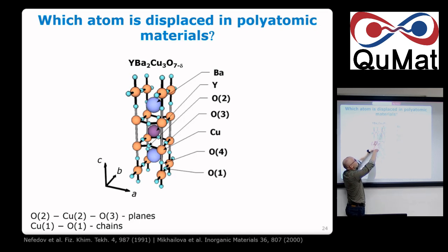Superconductivity comes from these planes. But once you change the oxygen content here, you are removing that one, or putting more oxygen here. Basically what it does is suck electrons, okay? The affinity of oxygen is to suck electrons. When it sucks the electrons, they come from this plane, and this is a hole conductor. So you generate more holes here and you improve superconductivity.